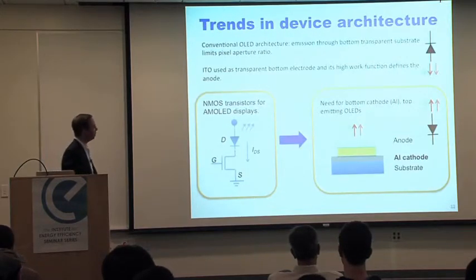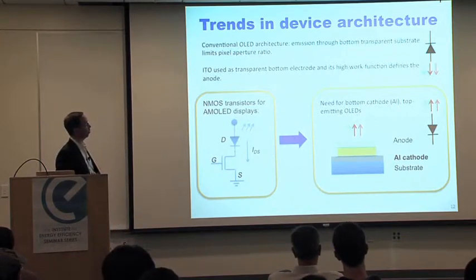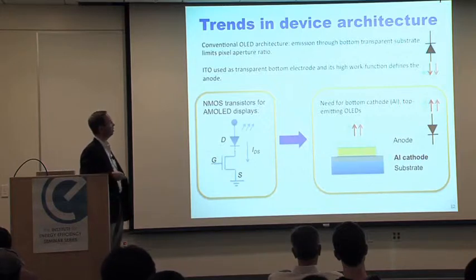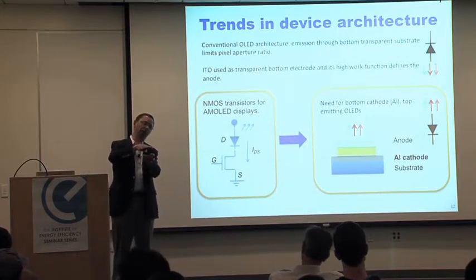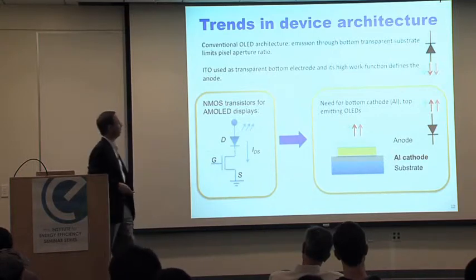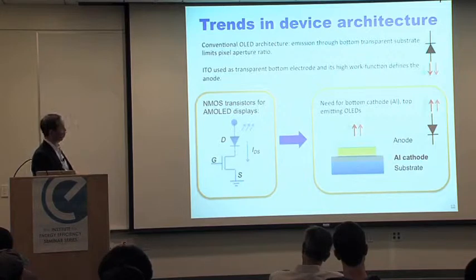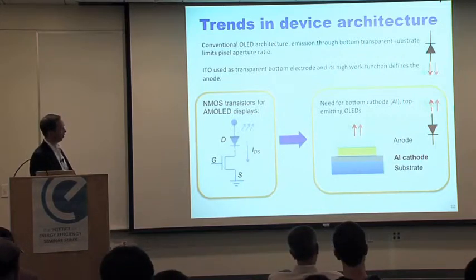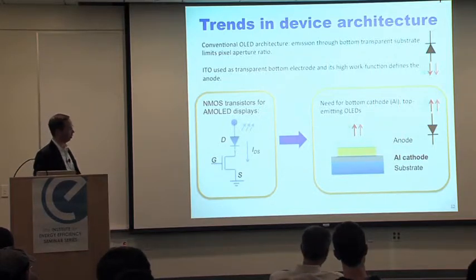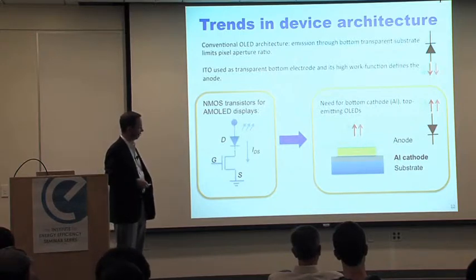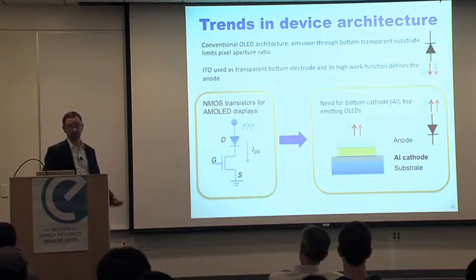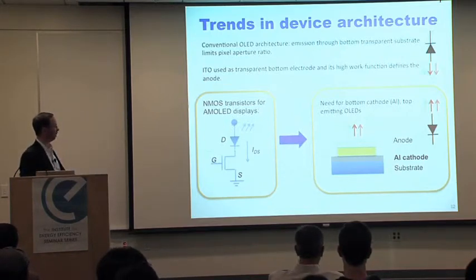And so some of the things we focused on recently is to change the structure or the geometry of the device. And so rather than having emission from the bottom, which limits, for instance, the pixel aperture ratio, if you combine these light emitters with a backplane technology, such as in an active matrix OLED display, you really have the advantage of having the emission take place from the top. And what we also did is we switched the polarity of the diode, namely we now have the buried cathode here, which is more reactive, at the bottom of the device, and the anode, which is made out of metals that have high work function and are environmentally more stable.